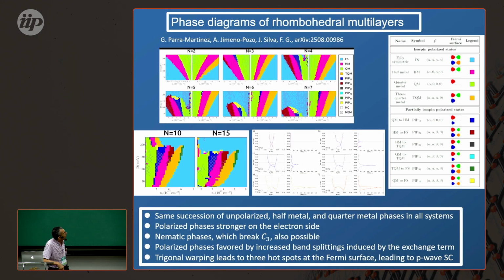These are our most recent results, going beyond 4 layers, and the phase diagram is very robust, no matter how many layers you include in the calculation. This is only Hartree-Fock, this is not superconductivity, we haven't finished those calculations yet, but we always get unpolarized, half metal, and quarter metal, and sometimes some nematic phases where the C3 symmetry is broken.